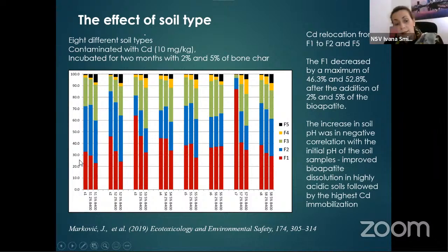What we could conclude is that the ion exchangeable fraction of cadmium decreased in all soil types. However, the effect was very different in different soil types. The exchangeable fraction of cadmium was decreased by a maximum of 46 and 52% with the doses of 2 or 5% of the bioapatite. And we also performed the correlation of the soil properties with the effect on cadmium immobilization and found a very significant correlation between the initial pH value of the soil and the immobilization effect of cadmium.